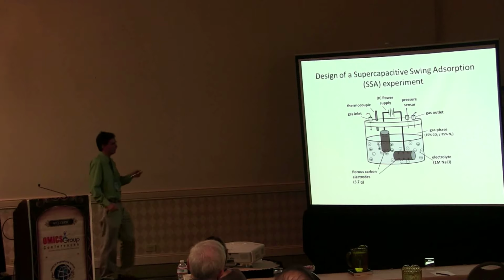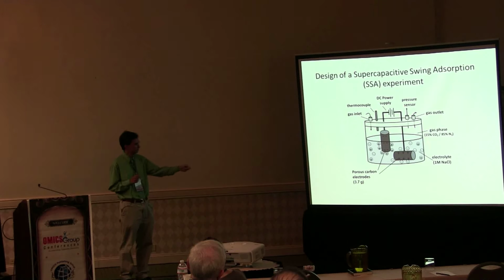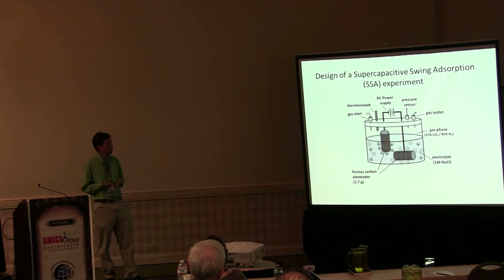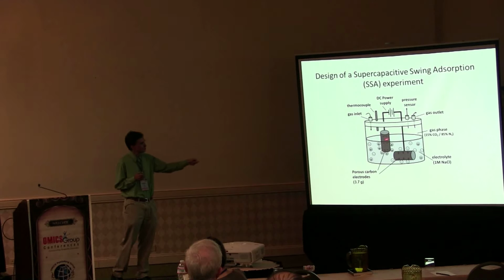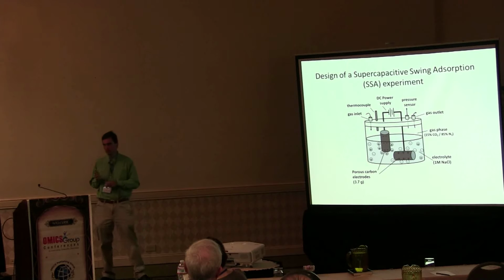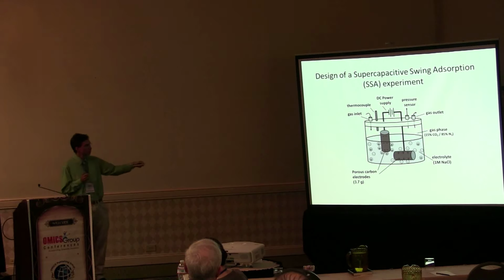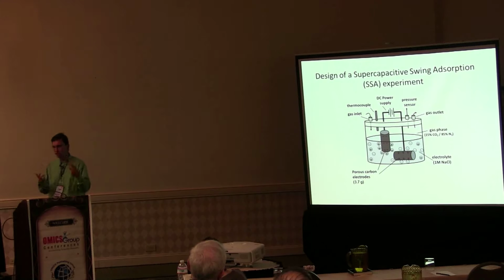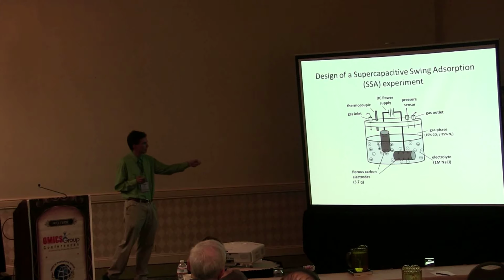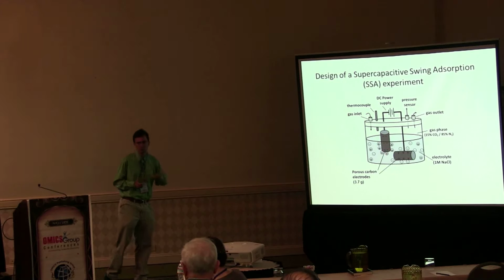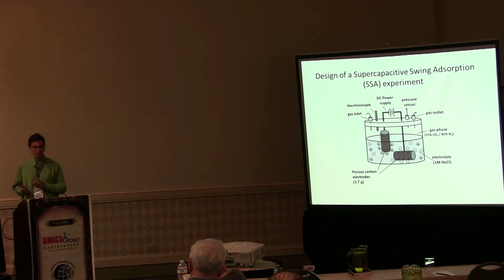You see here a gas adsorption cell. It has about 100 milliliter volume. This cell is half filled with a sodium chloride electrolyte. So you see two electrodes here. These are 3.7 gram nanoporous carbon monolithic electrodes. One is completely submerged. This is our counter electrode, which we consider to be isolated from the gas phase. The second electrode is partially submerged, so this electrode would be accessible for the gas.